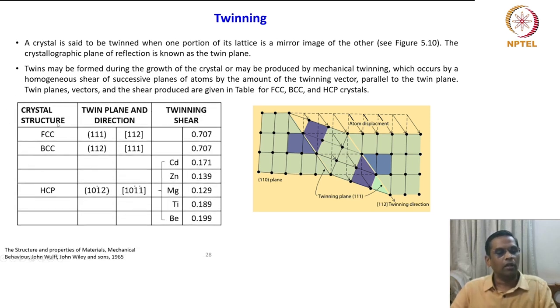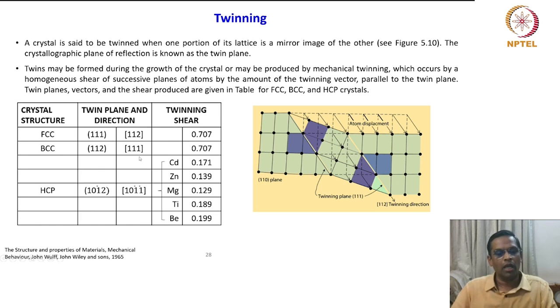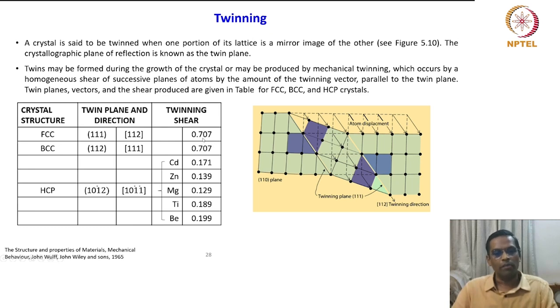For FCC crystals, the twin plane is {111} and the twin direction is <112>, with a shear of 0.707. For BCC it is the reverse — {112} planes and <111> direction, producing an equivalent shear to FCC. For HCP, the twin plane is (10̄12) and direction is [10̄1̄1̄]; examples include cadmium, zinc, magnesium, titanium, and beryllium. The twinning shear produced by HCP crystal systems is significantly lower compared to FCC and BCC.